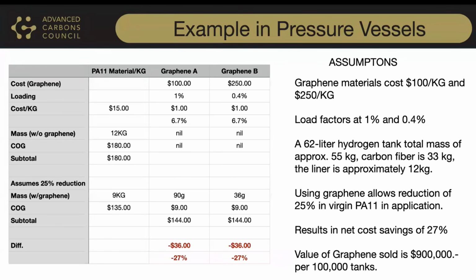So on the grid that you see on the left, the PA11 material for the liner costs $15 a kilo. There's 12 kilos of it, so cost of goods is $180 US. And then on the second column under graphene A and graphene B, graphene A is $100 a kilogram, graphene B is $250 a kilogram. Graphene A is added at a 1% loading, graphene B is added at a 0.4% loading because it's a different material. It ends up being the exact same cost per kilogram added at $1 each because of the different load factor, or 6.7% of the total cost.